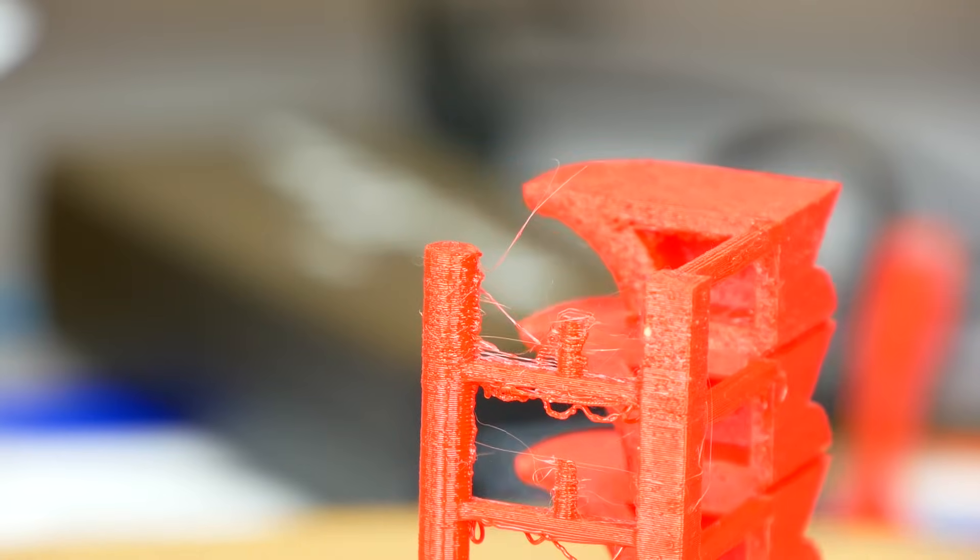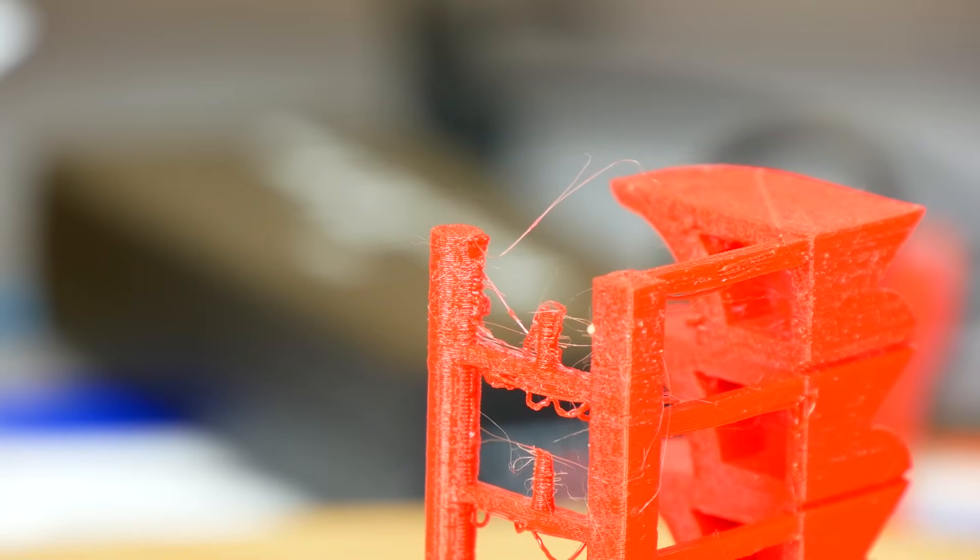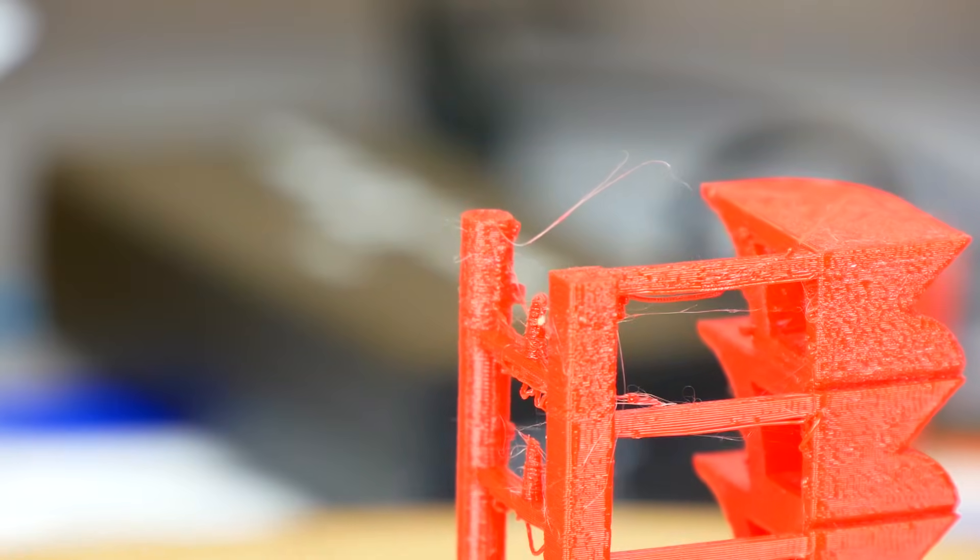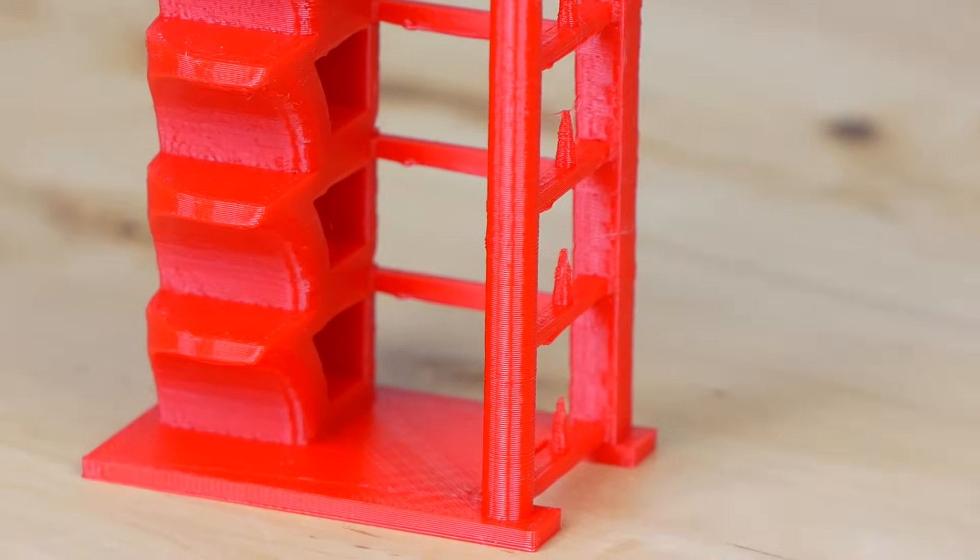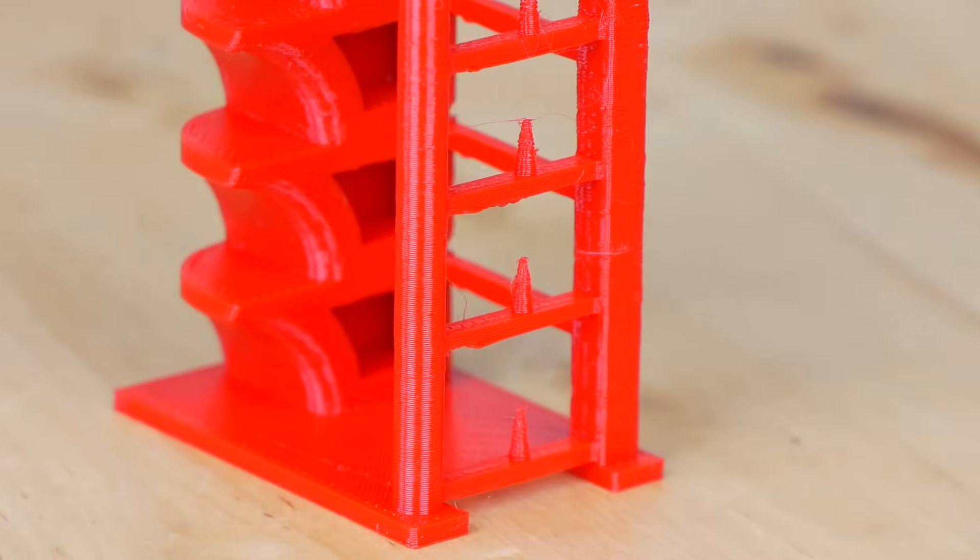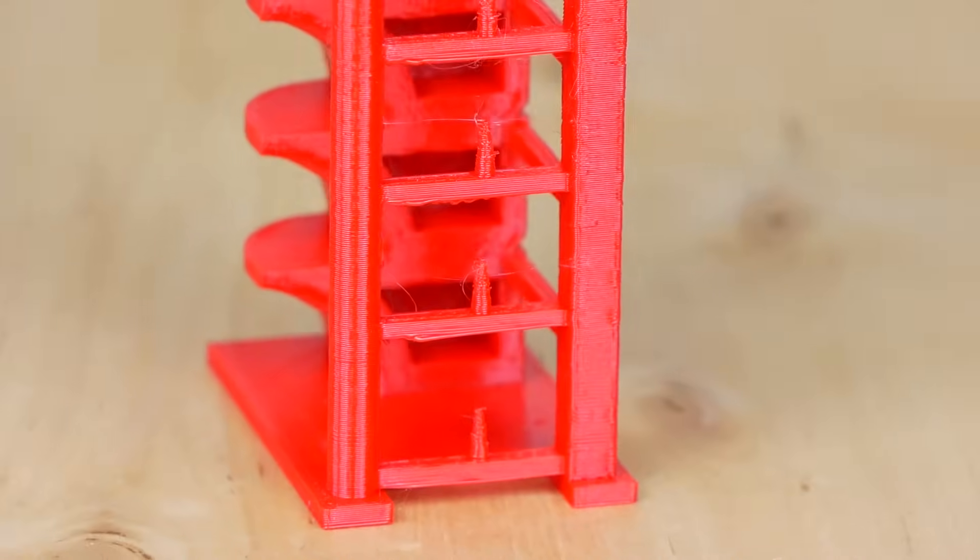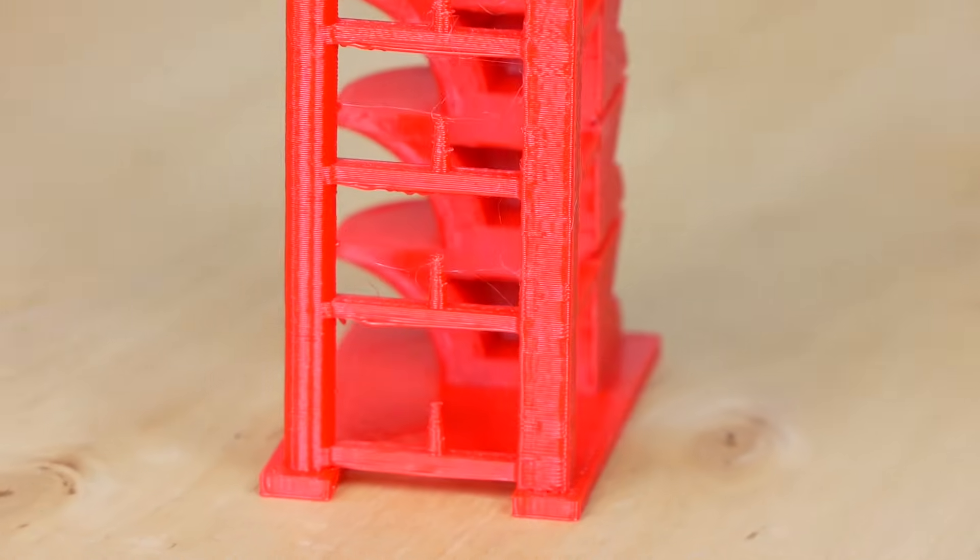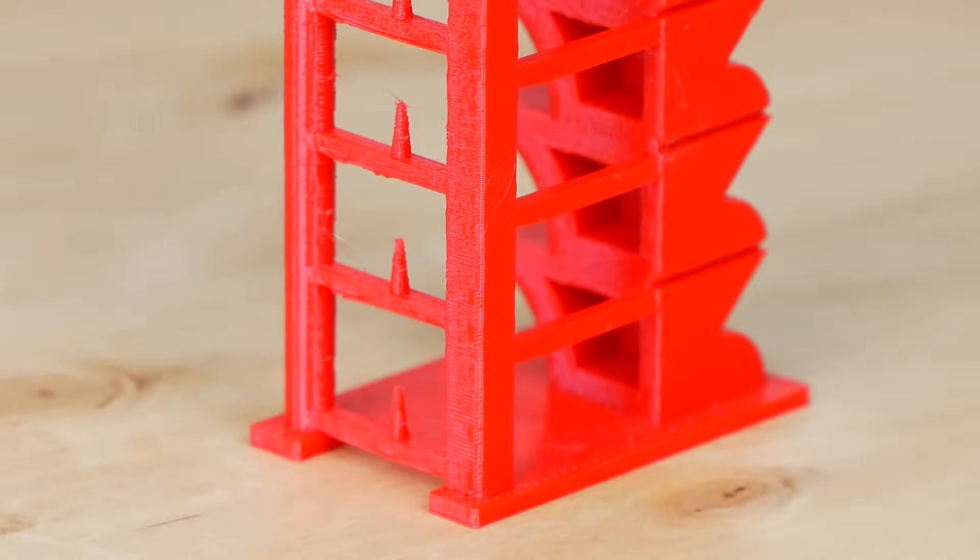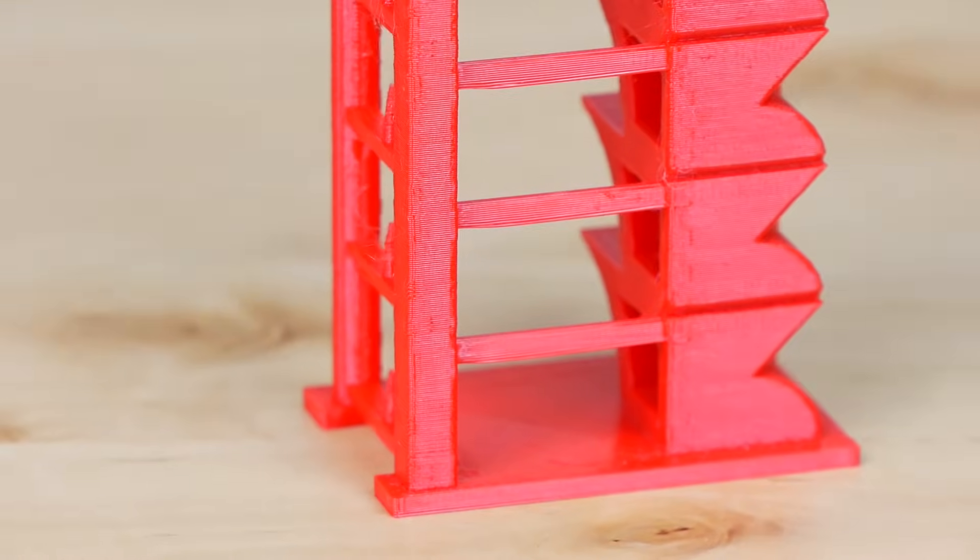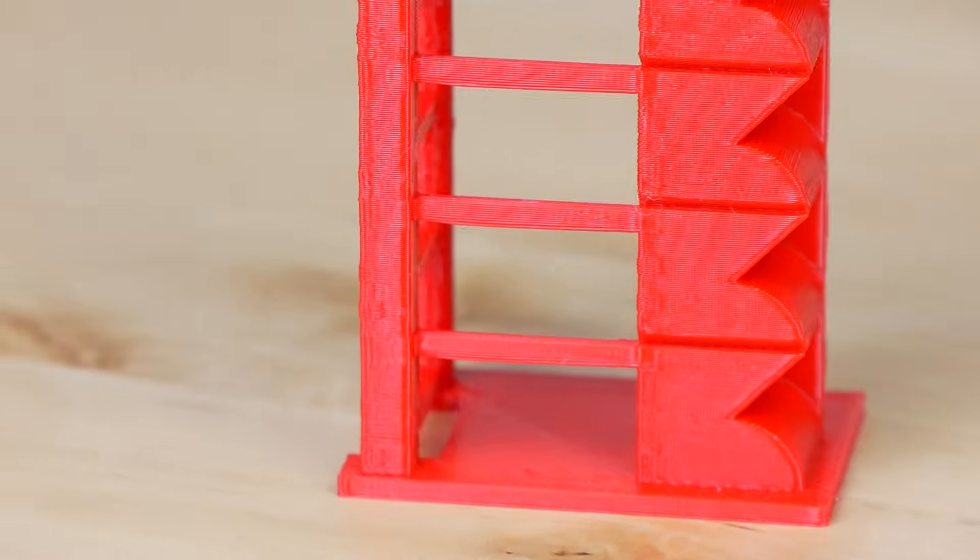Bridging became really bad for temperatures higher than 250 degrees Celsius. The fine details seemed to be printing well up to 235 degrees Celsius and then gradually become more and more squished out. So from these results, I would say that the printing temperature should be set between 205 and 235 degrees Celsius.